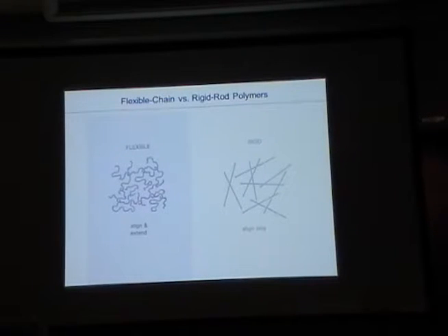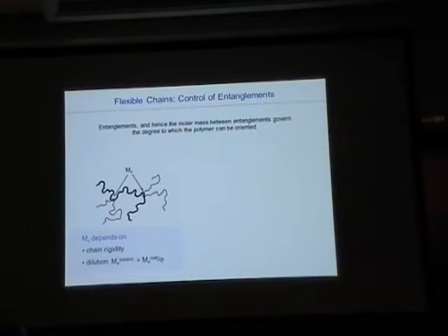Me personally, to be honest, I like flexible polymers. Because we have much, much more tools. Here we have many, many more little tricks we can play to manipulate the microstructure. And one of the key is entanglement. So it's like cooked spaghetti. And one critical parameter here is the molecular weight between these knots. We call that Me, molecular weight between entanglements. And this one depends on chain rigidity, obviously.